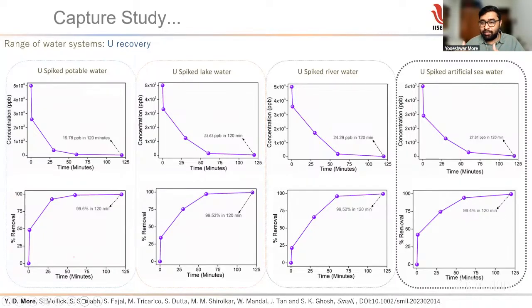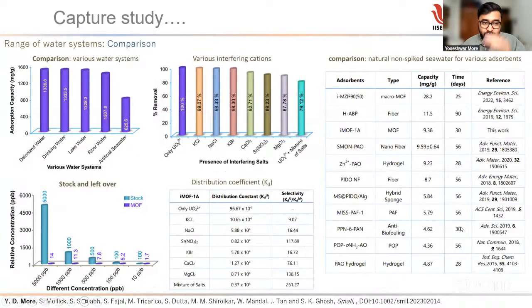Now you can see the removal percentage dropped by 0.1% in terms of artificial seawater. Why is it? Because there are interfering cations. But still the drop is not very significant, and we are able to get 99.4%, which is significantly higher than 99%, and hence our adsorbent has the potential to do this in a commercial setting. So finally, for the capture study, we have to go for the real seawater that we are going to do at the end.